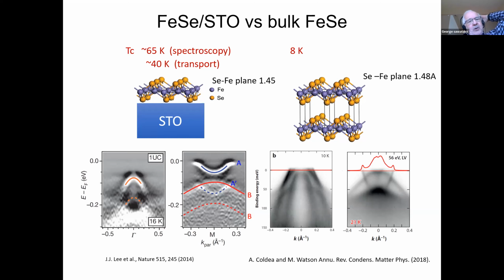The iron selenide on STO as a thin film or as a monolayer, of course, is even much more difficult. We actually don't know really, as far as I'm concerned, what the chemical composition is. We also don't really know what the structure is. But we know something about the electronic properties. And if you put iron selenide on STO and dope it with electrons, right, you get a transition temperature up to 65 Kelvin, at least from spectroscopy, and that's from tunneling or from photo emission, actually looking at the superconducting gap and so on. From transport, it's more like 40 Kelvin that you get.